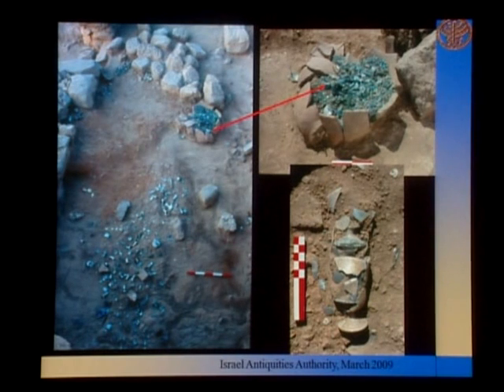A clay store jar was recovered in the storeroom. It was filled with small glass chunks ready for melting in the furnace. On the left of the clay jar is a pile of stones and red soil ready for repair of the furnace during work. On the bottom of the slide are vessels that fell off the shelves which were installed along the wall. The vessels were discovered one inside the other as they were stored on the shelves, as the wine glasses we see on the right.